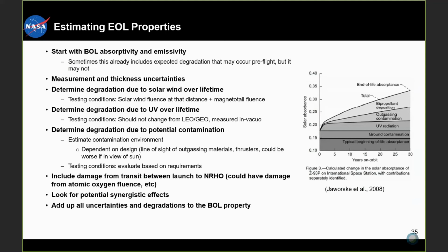So another factor that's expected to have a big impact for NRHO is UV, again, over the lifetime. So you'll want to do UV testing for each of your materials that you're considering. And one thing that's important with this testing is to do that in vacuum, as Abby mentioned. If you do the measurement after and you do it in air, then you'll get some bleaching effects, which will suggest that your absorptivity is much better than it actually is in vacuum. And then another thing to consider is that UV is not expected to be very different from LEO and GEO, so you can leverage some of the existing test data from that.